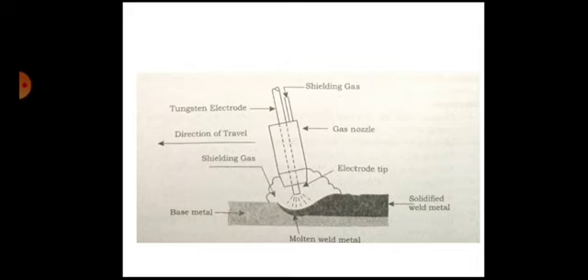All types of joints like butt joint, lap joint, corner edge and T can be made with this GTAW process. Single V joints are used for thickness up to 10 mm, while double-V is used for base metal thicker than this. That is all about gas tungsten arc welding, GTAW or TIG welding.